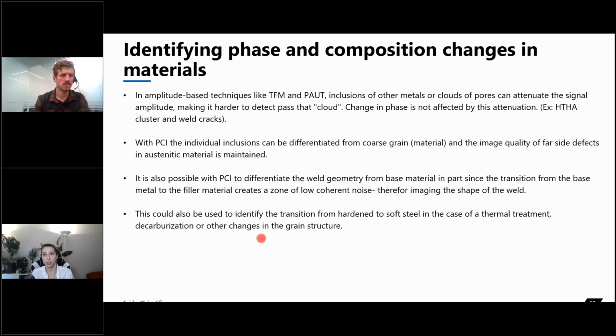So for example, if there's an HTHA cluster close to a crack that is occurring in the weld, same HTHA often will lead into a crack. So if there is a cluster that is very close to it, sometimes with amplitude, it's going to lose a lot of amplitude. And so with the phase, we won't have as much of that problem. Of course, as Trevor mentioned, the sound still needs to reach that area, but it becomes less of an issue in comparison to an amplitude-based technique.